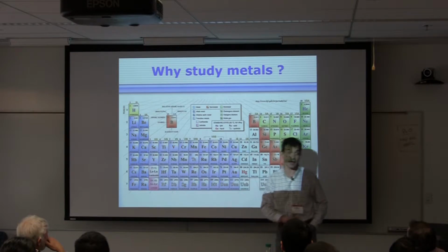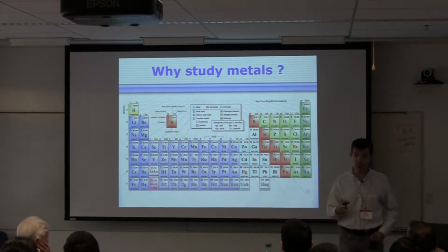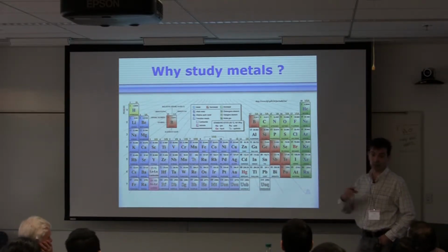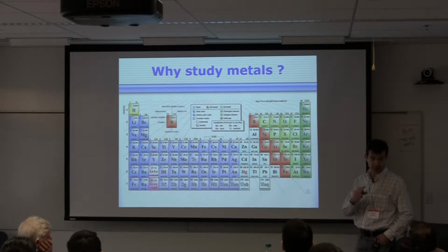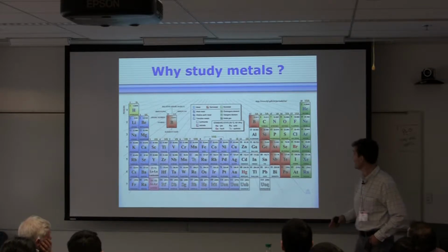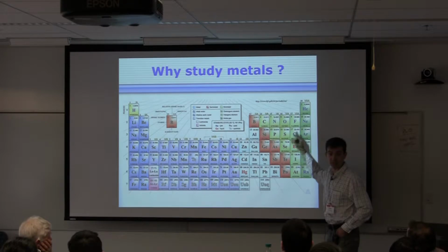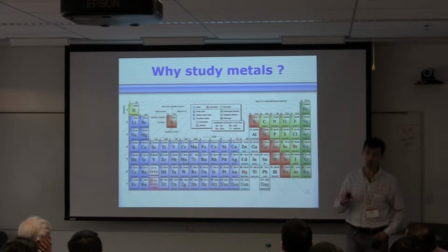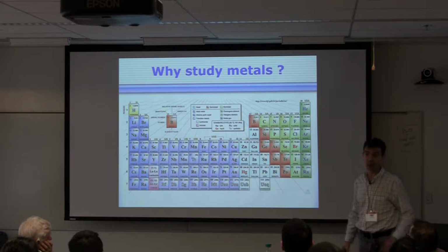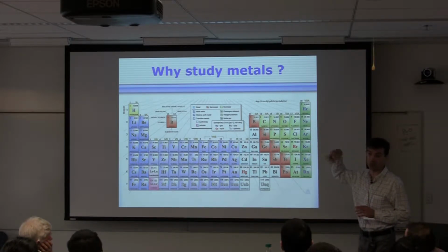Which means you buy cerium with 5 nines that has been electrophoretically purified and whatever. They tell you that it's 99.999% cerium, but they cannot certify oxygen, carbon, nitrogen, and other things in it. It's absolutely critical, because in many binary compounds it turns out that these non-metallic elements occupy interstitial sites. They're actually pseudo-binaries.